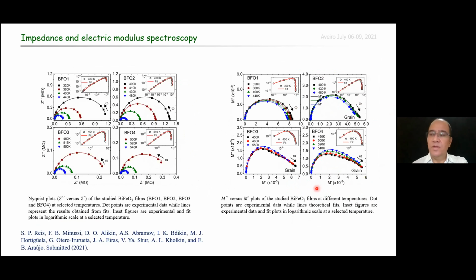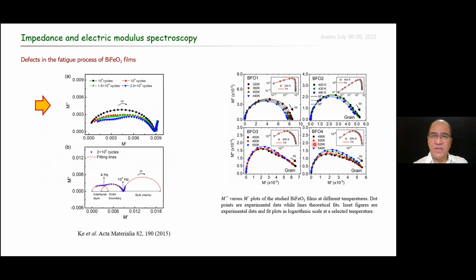In addition to DC conductivity, several parameters were obtained for all samples from fitting the Nyquist plots for impedance and electric modulus, as shown in these two figures. You can see in the inset plots a perfect agreement between experimental data and the theoretical model proposed to fit this data. From asymmetries on the Nyquist plots of electric modulus in this figure, we could infer about the defects in BFO films, similar to the fatigue effect observed in this BFO film also prepared by a chemical route.